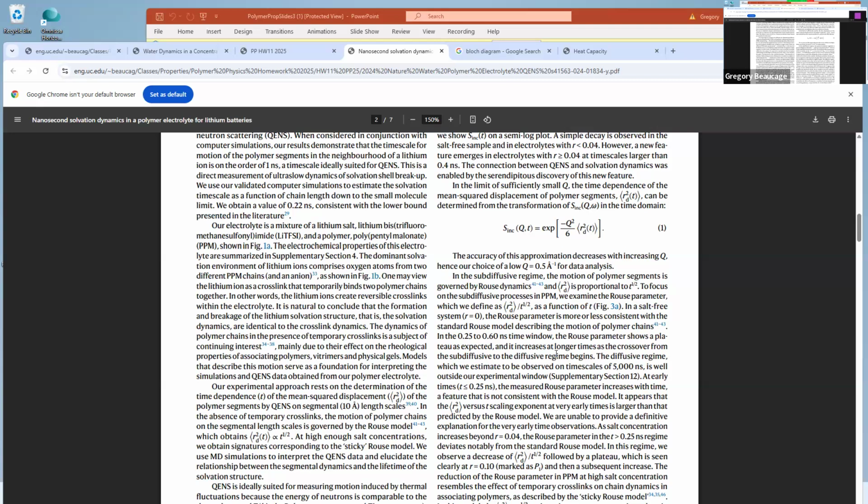So he's saying he could kind of get a Gaussian function at that size, which you don't see because it goes to persistence, right? So you don't see a Gaussian there. You see power 2 and then power 1. So there's no such thing. So it's a little odd what he's doing. I think he's just picking off a size where you could see a monomer, like a whole monomer.